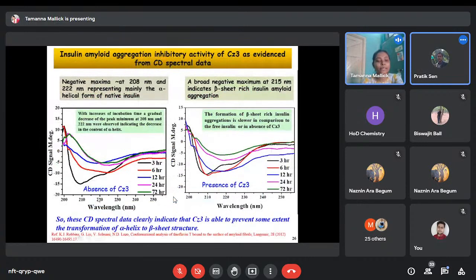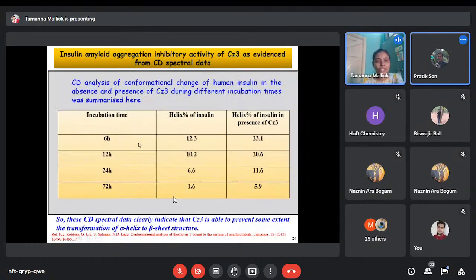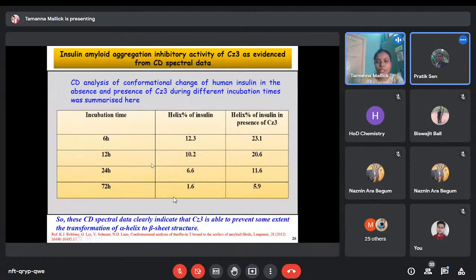Here, the CD spectra in the absence of CZ3 and the presence of CZ3. In absence of CZ3, with increase of incubation time, a gradual decrease of the peak minima at 208 nanometer and 222 nanometer was observed, indicating the decrease in the content of alpha helix. But in presence of CZ3, the formation of the beta-rich insulin aggregation is slower in comparison to the absence of CZ3. These are the summarized results of the CD analysis of conformational change of human insulin in the absence and presence of CZ3 during different incubation time periods.